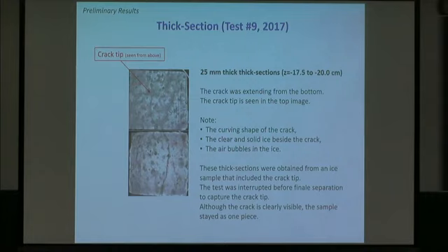So what can we say here? Thick section obtained from an ice sample included a crack tip. We interrupted the test, as I say, and we can clearly see this crack being open from this way and forward over here. After this we will also look at a thin section going from thick to thin section.